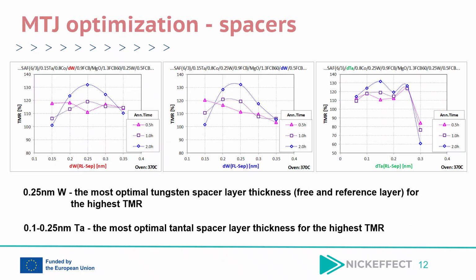After integration of the full MTJ stack, the next step was optimization of the spacer layers in order to maximize the TMR ratio. This slide presents the influence of tungsten and tantalum spacer thicknesses on the MTJ electrical performance for different annealing times. The left and middle graphs show the optimization of the tungsten spacer thickness used respectively in the reference layer spacer and free layer spacer. In both cases, the highest TMR values, exceeding 130%, were obtained for a tungsten thickness close to 0.25 nanometer after extended annealing. Further increase of tungsten thickness leads to a gradual reduction of the TMR ratio.